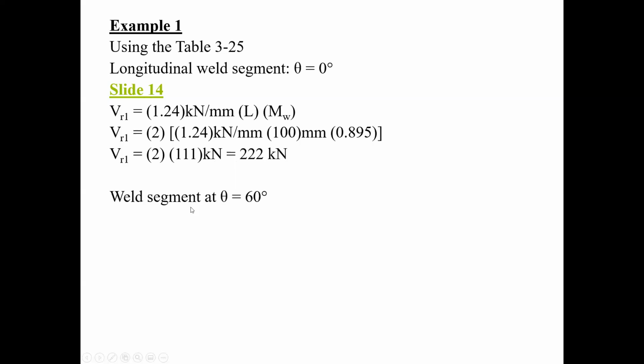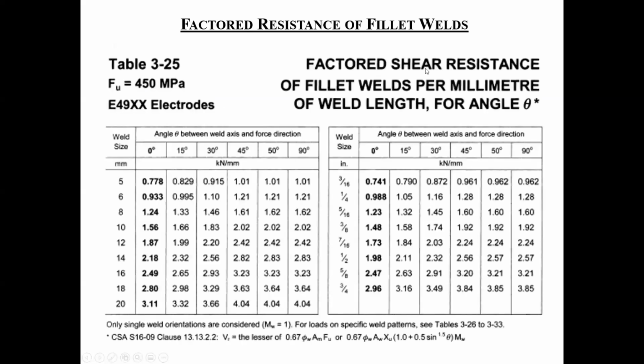Now, for the weld at 60 degrees, I'm going to go back to slide 14, and here we go. For example, I have an 8 millimeter weld, and the orientation is, well, here it doesn't make much of a difference. Between 50 and 90 degrees, it's exactly the same value, you see? So even though I have 60 degrees here, it would make absolutely no difference. This is what I'm telling you, the table already takes into account this equation here. That's why it limits what the resistance is. And therefore, I have 1.61.